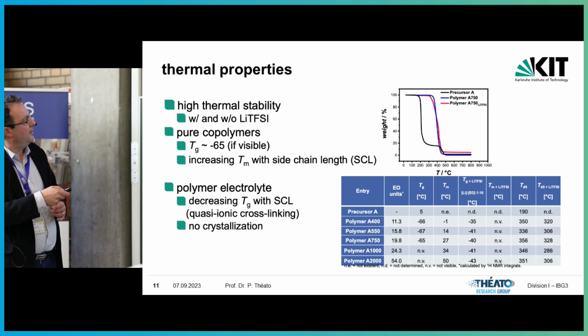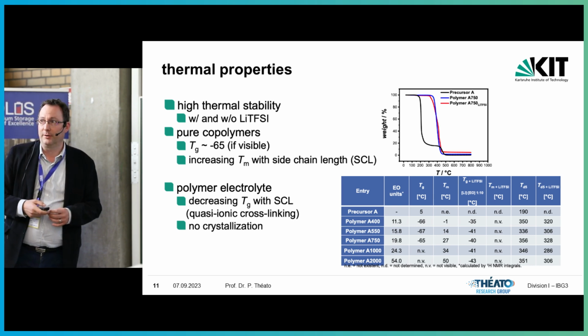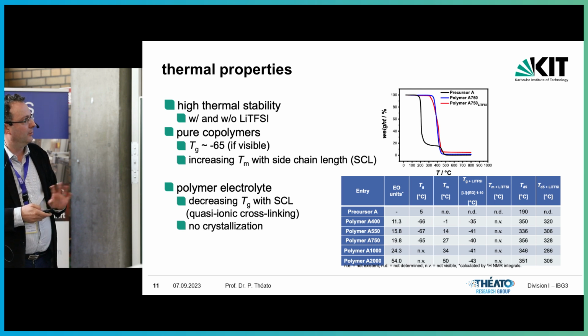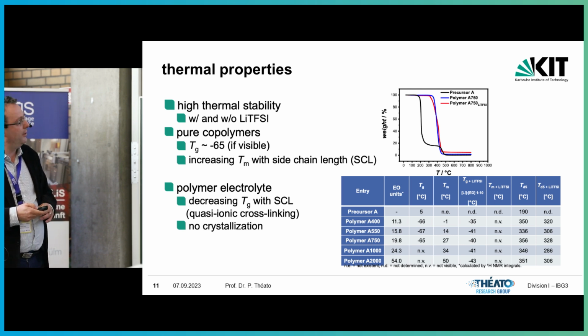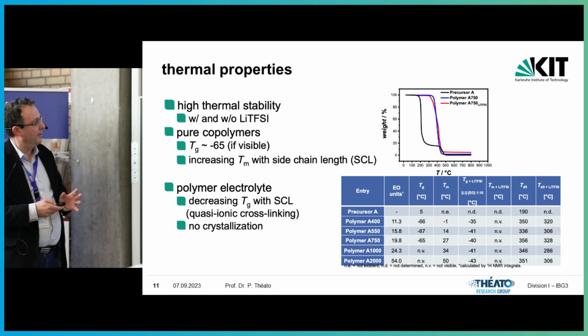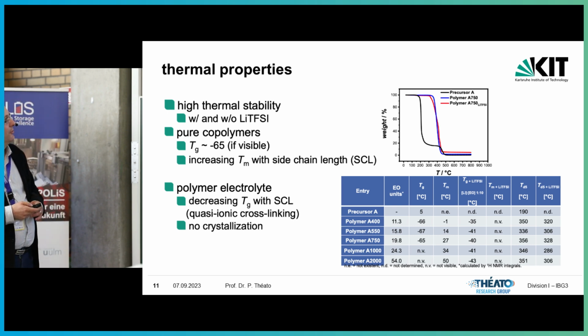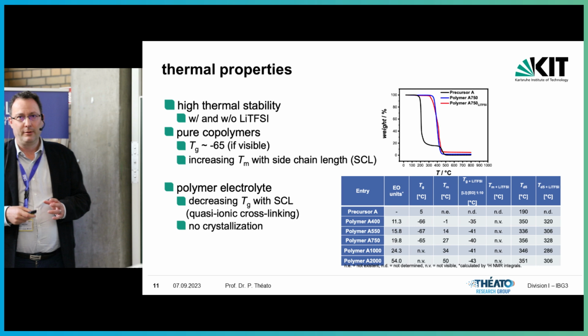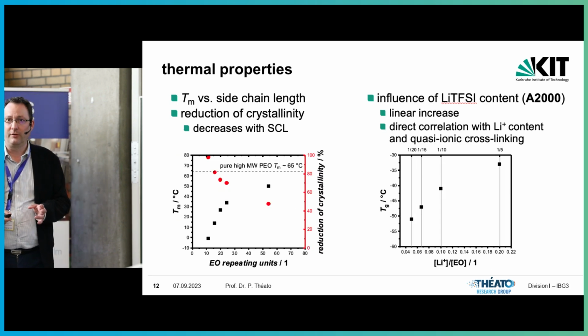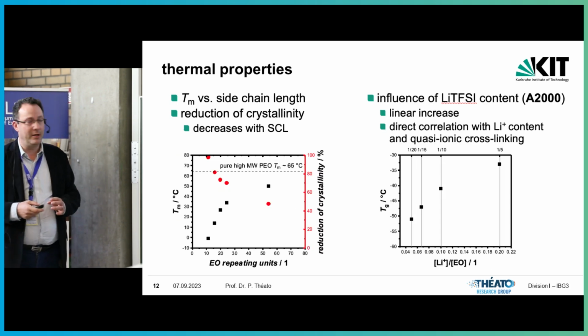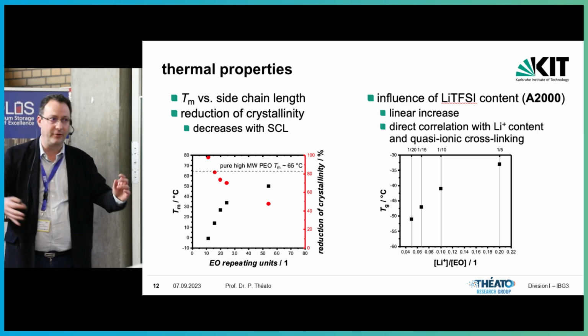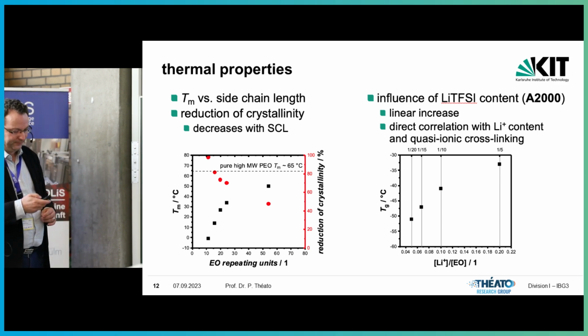But this all changes as soon as you add lithium salt. Okay, then we can completely avoid any crystallization, but it affects the glass transition temperature. And this is what you see here. For example, for one system with the longest side chain, depending on your lithium to ethylene oxide content ratio, the glass transition changes, okay? So we do have what we call a quasi-ionic cross-linking in the system, and that alters the glass transition temperature.